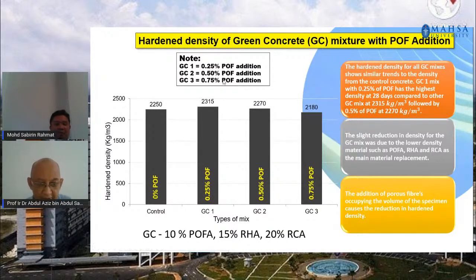So then as you have more fiber, the result shows a slightly lower density than the 0% palm oil fiber of the green concrete. But then again, in saying that, the results are almost quite similar in terms of density. So roughly, I could say, nearly 2,300 kilograms per meter cube of green concrete density was achieved in this study.